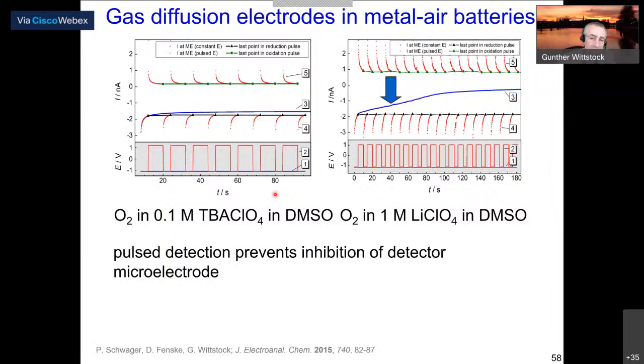So I remembered my old history in analytical chemistry, and there's a process which is called pulsed amperometric detection. So I said, okay, let's do that. After a reduction pulse with the microelectrode, we clean the microelectrode by an oxidative pulse, removing whatever was maybe deposited on the microelectrode, because this looks to me like deposition or passivation of the microelectrode. And then when this is clean, we start again a reductive pulse, and then we clean again. Measure, clean, measure, clean. And then we get these transients.